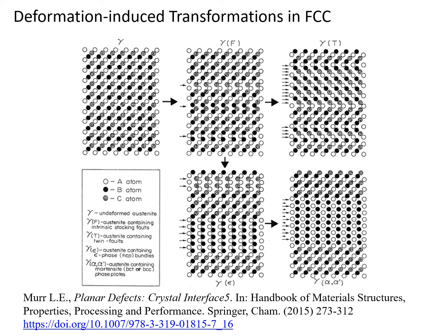If you just sheared individual planes a little bit, so we sheared here, this plane, along this direction, that creates what's called a stacking fault. So you can see how, instead of being all nicely arranged, the atoms here in the 111 directions, they're actually a little jog, and that's a stacking fault.